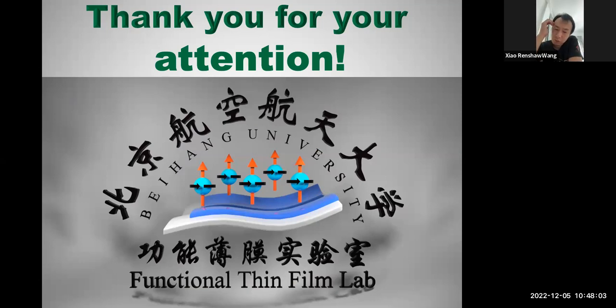Hi, Zhiqi. So recently we had also looked at PMN-PT substrate. So we thought probably we can also do some strain effects. But when we got the PMN-PT and we did AFM, we realized that the PMN-PT surface is a bit rough. So then, for example, if we want to grow ultra thin films, we haven't done it, but we felt it's maybe a problem because there could be a leakage or could be discontinuity or cracks. So did you encounter a similar problem, or did you polish the PMN-PT and make it very flat?